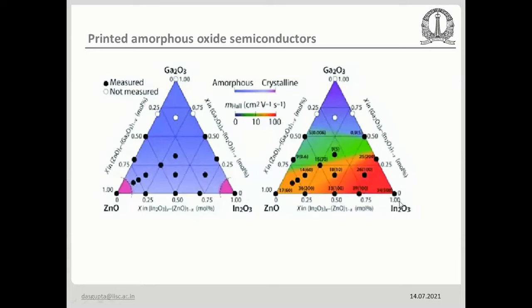So you can see pure indium oxide has the highest mobility, and of course gallium oxide is bad. If it is crystalline beta gallium oxide, it can be very high, but to get there you need very high temperature, which you cannot do on inexpensive substrates, right? So for amorphous gallium oxide, mobility is very low, but you can find the contour here, where indium oxide is higher in amount, with some zinc and some gallium, it is amorphous, but the mobility is also not that bad, and that is what we use.